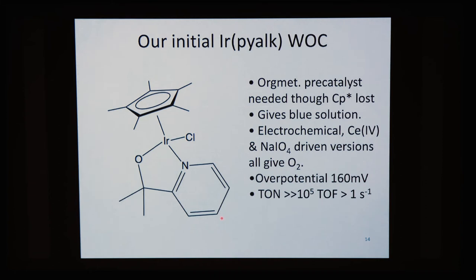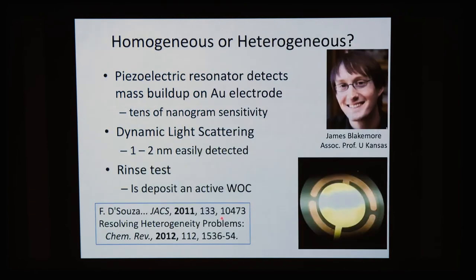The overpotential is 160 millivolts. We need a low overpotential because this is the potential above the thermodynamically required potential. So obviously for high efficiency, we want that number to be low, and 160 is very good. The turnover number is greater than 10 to the 5. In fact, a company looked into this compound and ran it for 10 to the 8 turnovers. So this was very robust, and the turnover frequency is 1 per second, so that's not too bad.